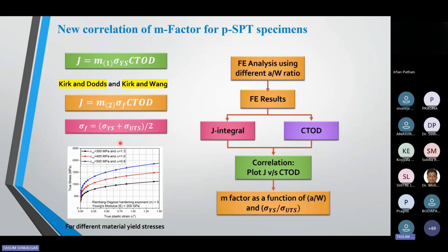So how can we utilize a numerical methodology approach to find out this factor, because this factor is a function of the geometry as well as the material property. So we decided to use multiple properties. I am just showing this one curve. Here we generated this curve by varying the yield stress. This is for 300, 400 and 500 MPa. One is alpha, the Ramberg-Osgood parameter.